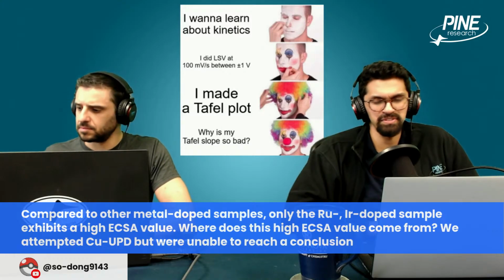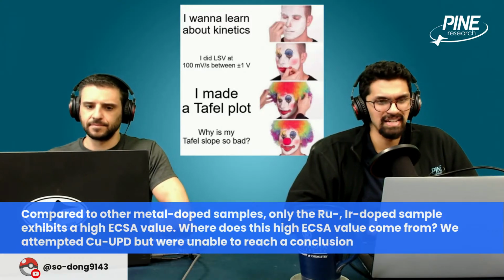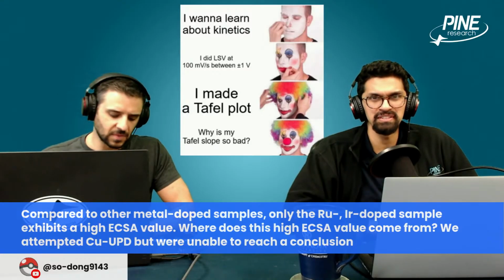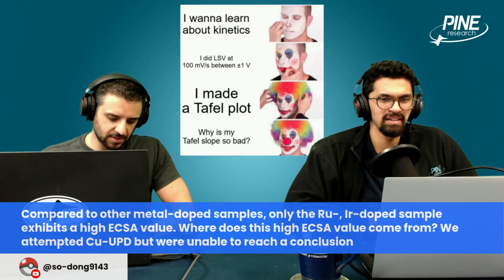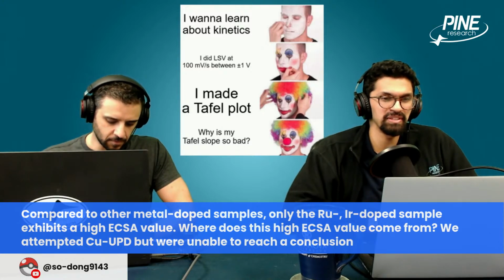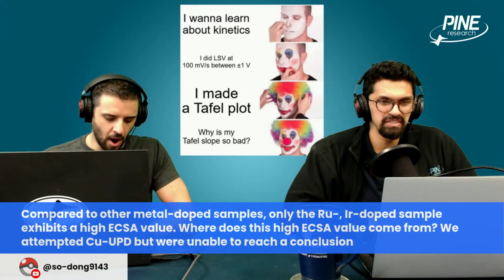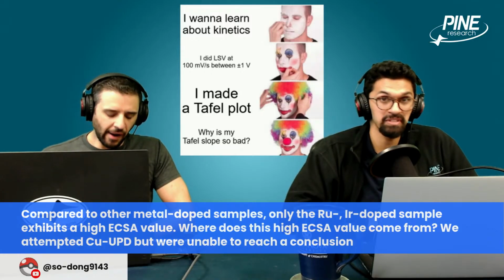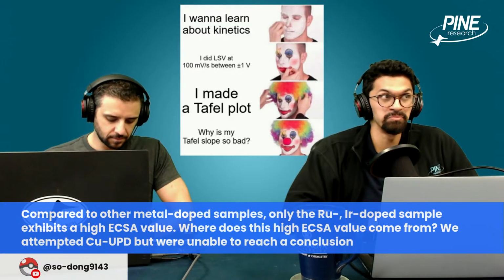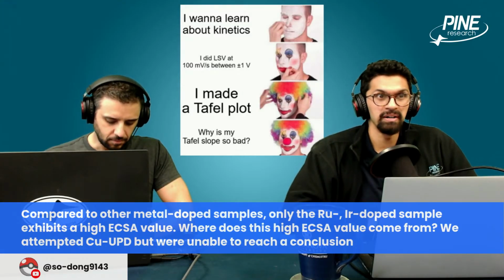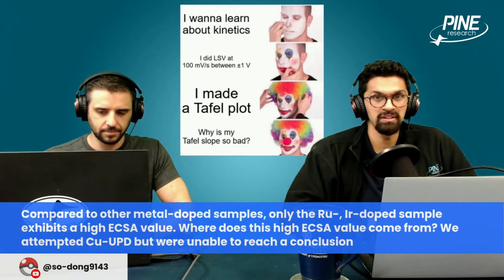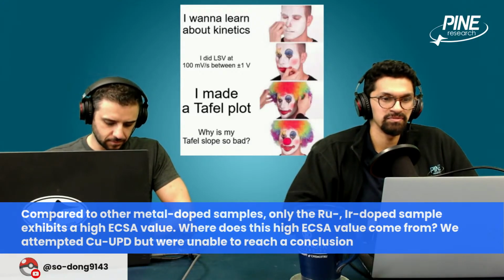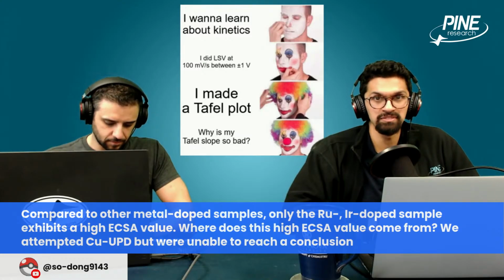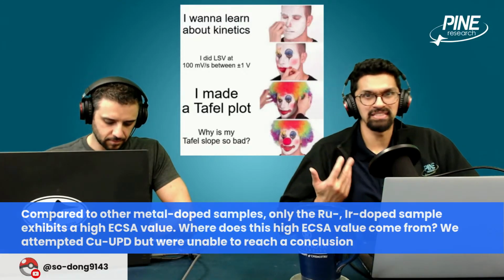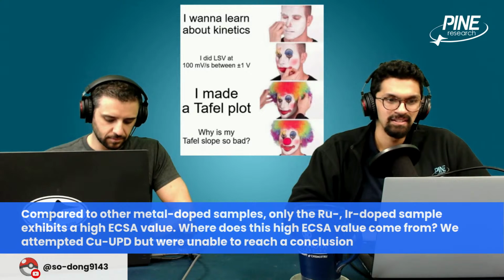I'm also wondering, are you using a technique like hydrogen adsorption to determine the ECSA? What is your method? Because it's possible that hydrogen has a natural affinity for ruthenium and iridium, but not so much for copper. You could be depositing the same amount of copper, but it doesn't have a high affinity for hydrogen bonding, or formation of hydrides as you would with ruthenium and iridium, that lend themselves to giving you very high ECSA values.